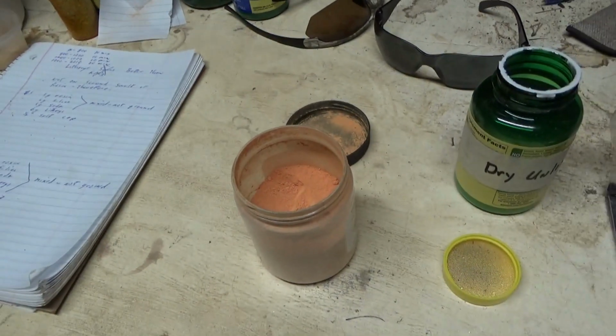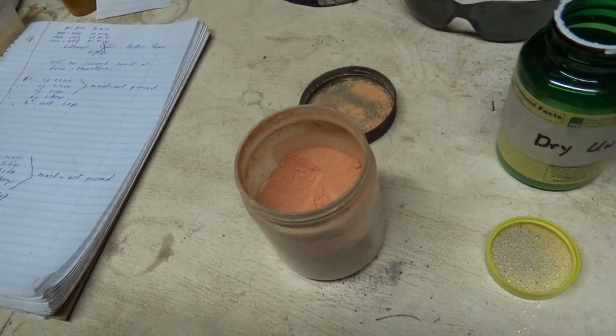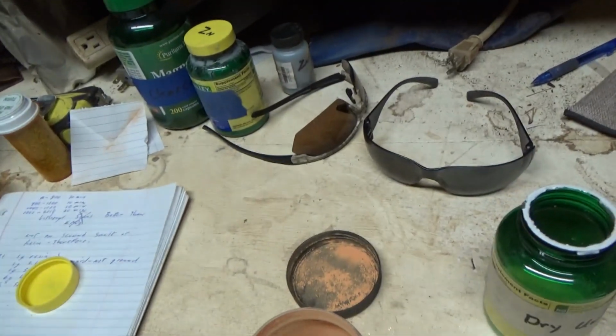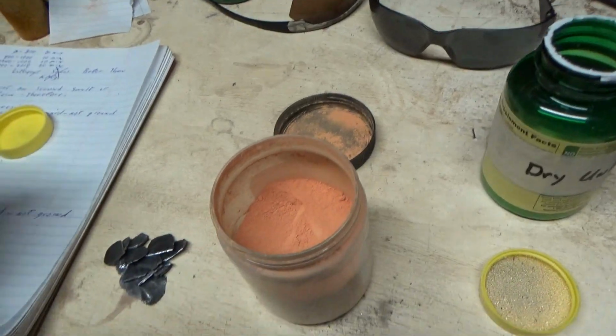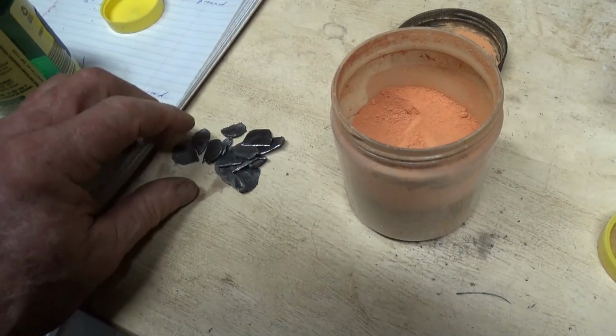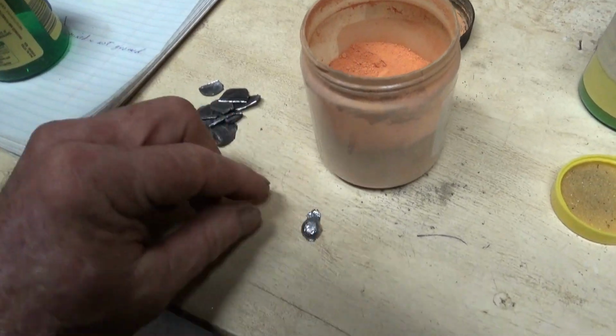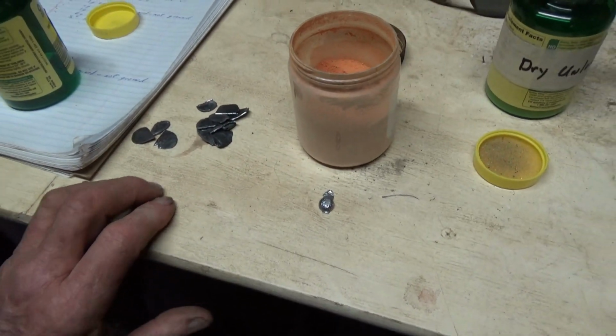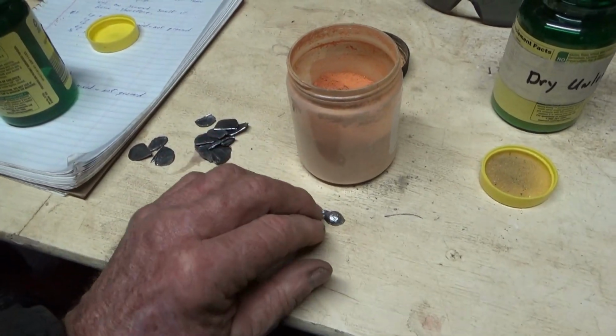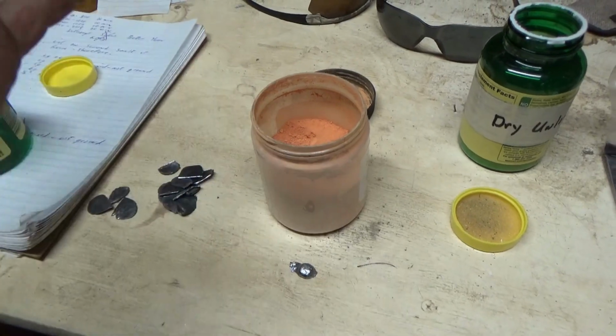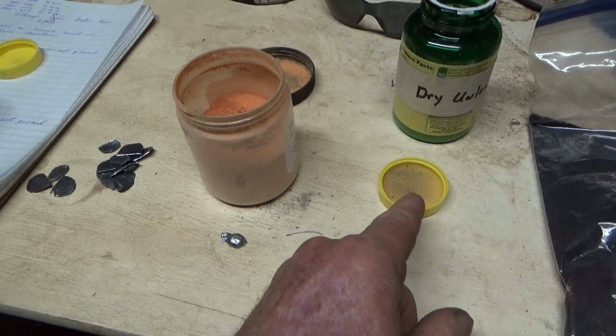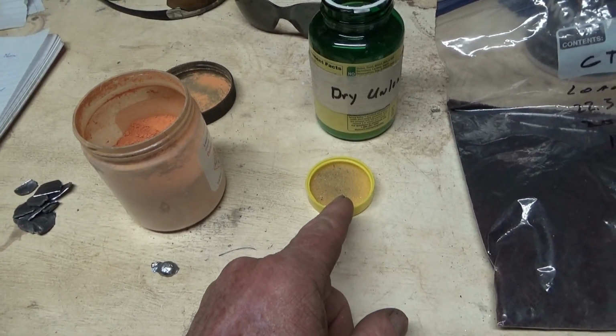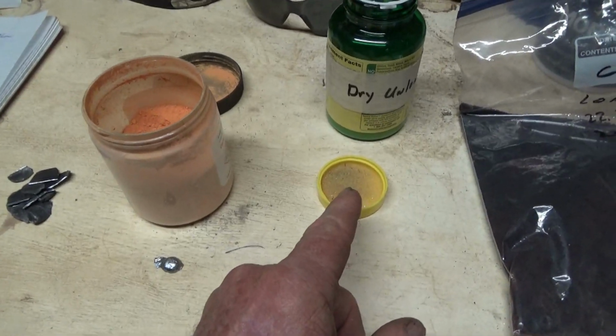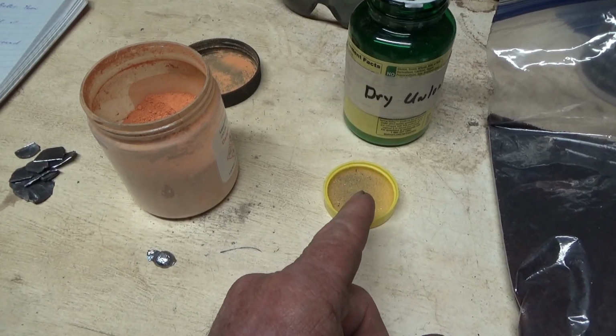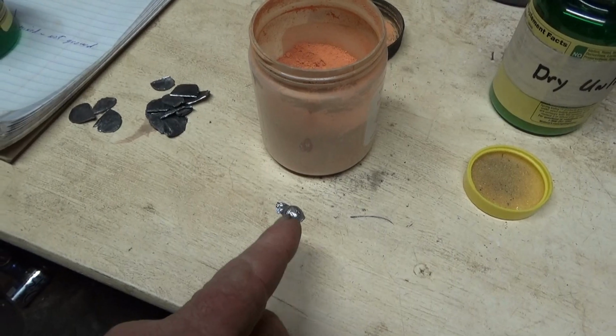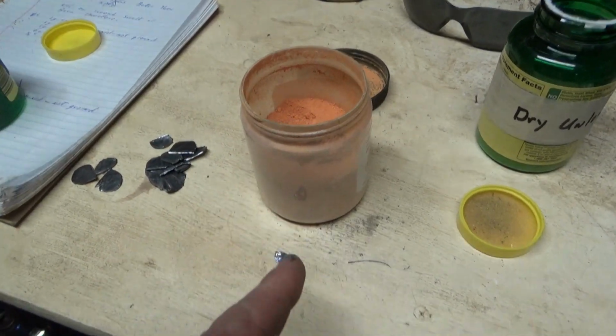And in fact, let's see, where is it? This was the lead that I recovered yesterday from 6 grams of that, using the same formula, and 1 gram of the resin. This basically provides carbon and hydrogen to suck the oxygen away from the litharge to create lead.